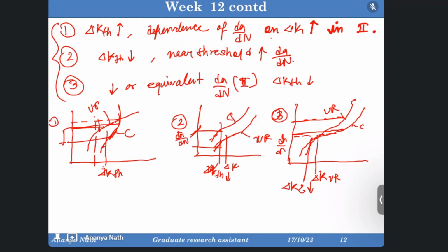Again, it depends upon the stress ratio that you are applying. At the time of fatigue testing, you can control the stress ratio, but at the real application site, you cannot control the stress ratio. So depending upon the real application site, you are applying the stress ratio here. So you don't have control on that. But what you have control on is the percentage reinforcement, the particle size, and the interface bonding and those things. So this is why we are more concerned about the reinforcement rather than the crack propagation.